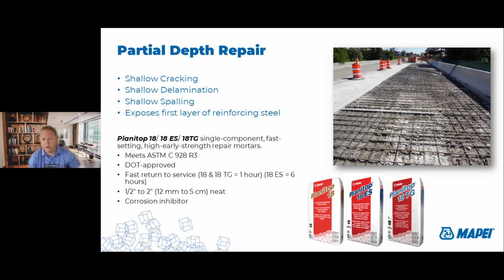So for partial depth repairs, you could have shallow cracking, delamination, or spalling. For these repairs, you're going to be exposing the first layer of your reinforcing steel. A great product for this is Planitop 18. We have an 18 extended set, which gives you a little bit more working time, and then also an 18 TG trowel grade. This product is approved on most DOTs here in the U.S., and this has a high early strength. Like I mentioned, you're going to be over 3,000 psi in under an hour.